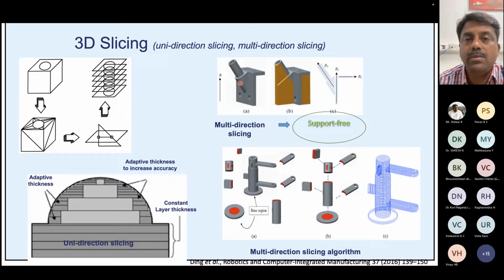In a powder bed, we may have to deal with support structure, the support structure that you see here in the orange color. If we want to produce this part without support structure, say in a powder bed, it is not possible. But when you use a DED process, we can also manipulate the direction. What I showed you in the video in laser and powder, the build platform can also be rotated. So for that, we need multi-directional slicing. We can start printing only the B1 part of it, and then subsequently the build part can be rotated 90 degrees and then build the B2 part, and then 45 degrees for the B3 part to produce support-free objects. And this is what is known as multi-directional slicing, to produce such overhanging features.